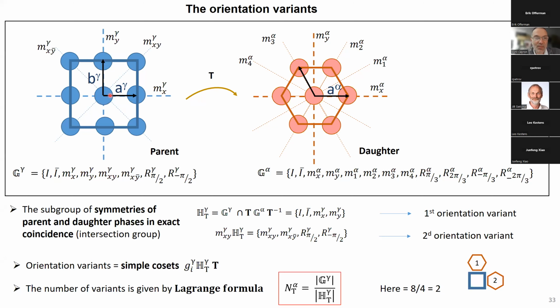But some symmetry elements here are common to the square and to the hexagons here. This symmetry element is common here, so it will not create a new variant. It will remain the same variant. And it's the same for this symmetry element here and here. So if I calculate the orientation relationship and I multiply on the left by one of the symmetry elements, I change nothing. And these symmetry elements that are common to the parent and the daughter variants here are written here.